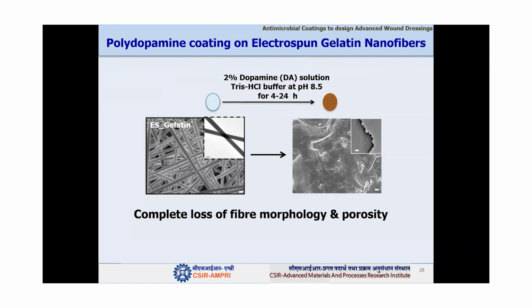So we did the same thing which is available in the literature. How they were coating it, as I have mentioned, is that any substrate you put in the dopamine solution at high pH, you will get the coating. So that is the same thing we did. We took the gelatin nanofibers. You can see very beautiful nanofibers of gelatin, which have a diameter of 300 to 350 nanometers. And this is the TEM picture of the gelatin nanofibers. And then as soon as we put them in the dopamine solution at the pH of 8.5, this happened. The whole nanofiber morphology got deteriorated. So complete loss of the fiber morphology, which we don't want. So we thought, then, what to do.